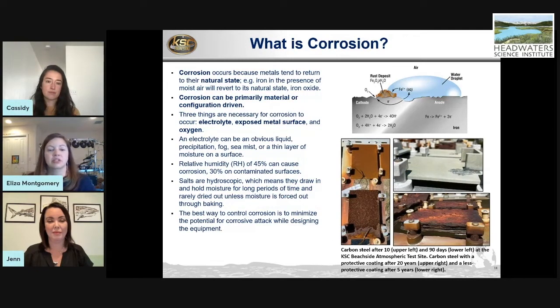And it's important to know that even a humidity of around 45% can cause corrosion, and on a contaminated surface it can be even lower, because salts are hygroscopic. What that means is they draw in moisture and hold it for a long period of time. The only way to truly dry out salt is to put it in an oven and drive the water out above the boiling temperature of water.